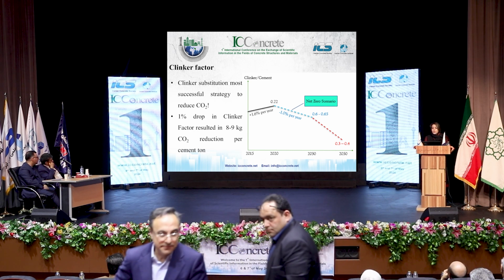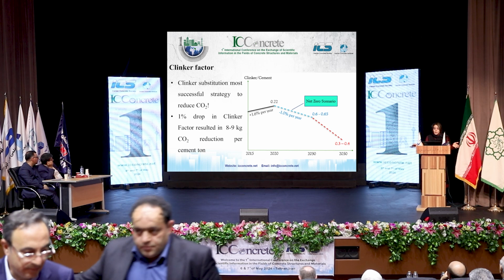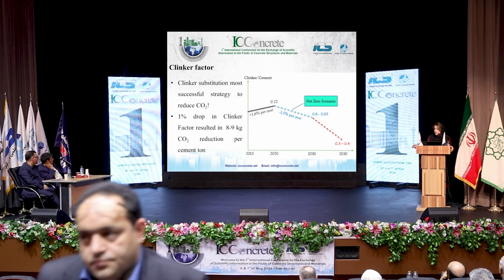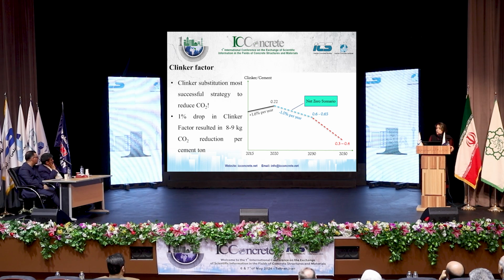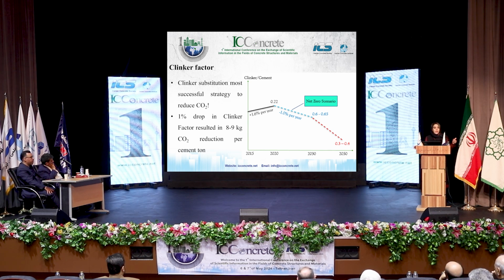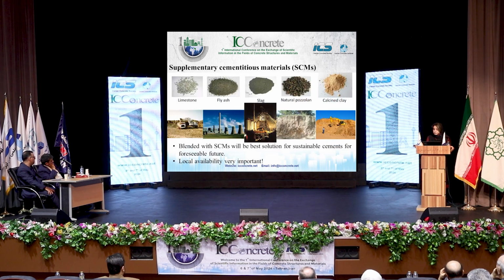Clinker substitution is stated as a successful strategy, and with each 1% drop in the clinker factor, we can have 8 to 9 kilograms of CO2 reduction per ton of cement produced. One of the best solutions for achieving the foreseeable future is the use of SCMs.